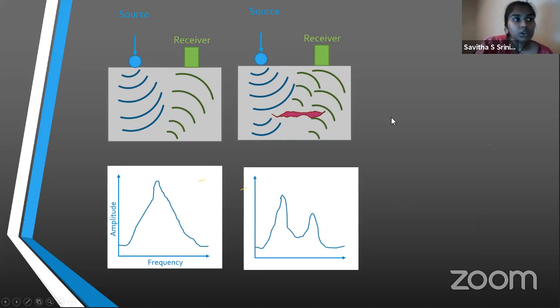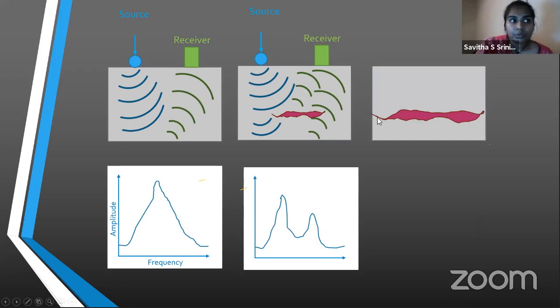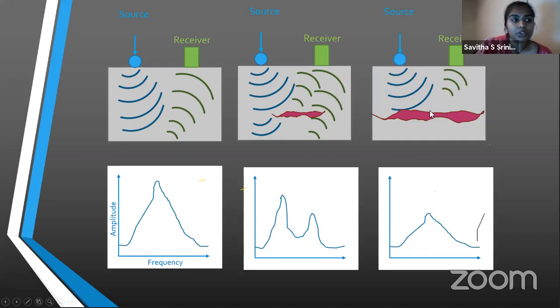Now, assuming your flaw extended throughout the specimen, you would have just the source wave hitting the flaw and bouncing back to the receiver. So you'd have a much smaller amplitude when you compare it to the undamaged specimen. Essentially, you can detect what kind of flaw you have and how big your flaw is using the impact echo method.